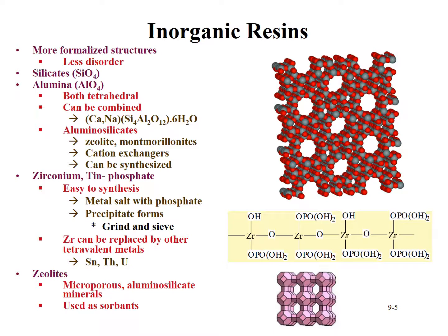An example of an inorganic resin material that is relatively straightforward to synthesize is zirconium phosphate, with a structure shown here. If you just take a metal salt with a phosphate solution, you can have a precipitate which forms, which has a fairly regular structure, and you can tune the gap between the metal ions, with this bridging oxygen, by choosing the metal ion itself.